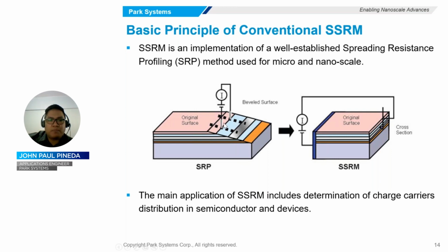Also in SRP, the tip curvature radius is larger, about 10 micrometers, and the material is a tungsten alloy stylus. While in SSRM, the tip is very small, only about 50 to 100 nanometers or even smaller, and it is a diamond-like carbon-coated tip. The main application of SSRM includes determination of charge carrier distribution in semiconductors and devices. Later on, I am going to show you some examples of each application.